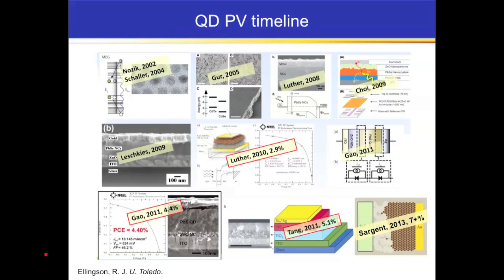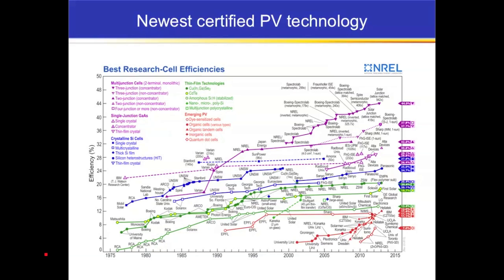The quantum dot PV field is only about 10 years old. It started really with Nozik's theory and general discussion paper in 2002. And then you can see the progress here. This was our paper in 2008 looking at the Schottky devices. And by changing then to a PN heterojunction kind of device geometry, we can see big improvements in the efficiency. And today Sargent's group at the University of Toronto is leading the field in terms of efficiency, somewhere around 7.5 or 8%. And this technology is now actually certified.